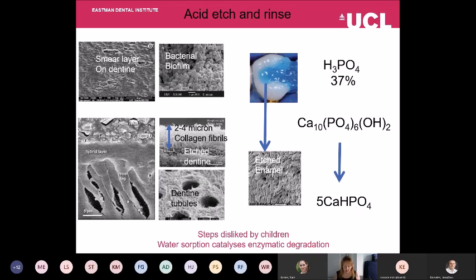So what you need to do is have a primer that can penetrate deep down into these tubule structures and also penetrate into the collagen fibrils. What you form when you polymerize the primer is tags of polymerized resin that seal up the tubules, and on top of that a hybrid layer.